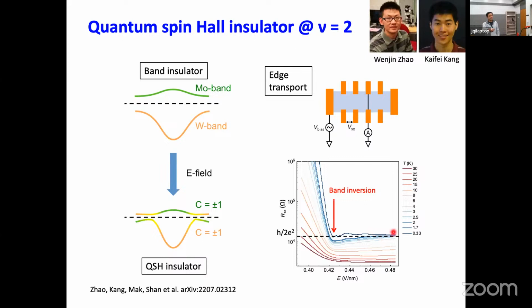It's not very clear in this log scale, but you can see that the resistivity saturates with temperature, and it also saturates with electric field. You can see an electric field plateau, where the resistivity is nearly independent of the electric field after band inversion, which is totally different from the behavior before band inversion. Okay, so this suggests that we actually get a topological state after the band inversion.